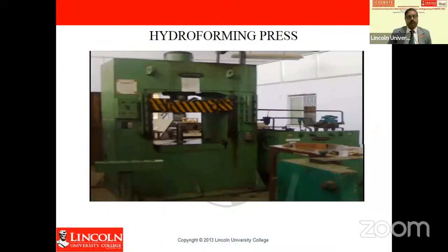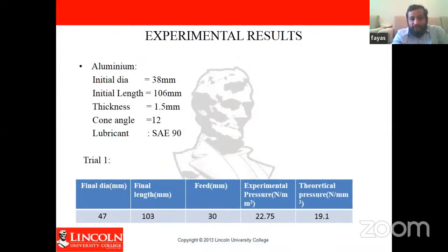This is the hydroforming process. We changed the tool setup. It's the same one that we have shown, and from this one, we did the process. The diameter of our tube is 38 millimeter. Thickness is 1.5 mm. First we did a trial at 30 millimeter feed.